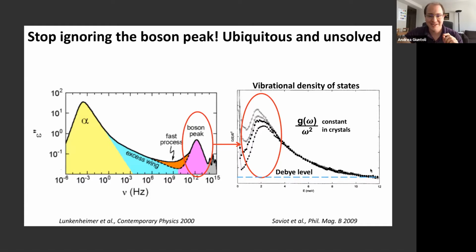The reason why this peak at the terahertz is so important is that we are talking about solids now. There's no escape from the cage. There's just rattling motion and vibration and phonons moving around the material. And from the theory of crystals, we know that if you take the density of vibrational states at this frequency, it should behave like omega squared, like the frequency squared. That's from the Debye model. And so if you plot the density of states g of omega divided by omega squared, you should see this blue line, a constant, which is the Debye level, which is related to how waves and phonons move in the material, and to the material's elastic properties.